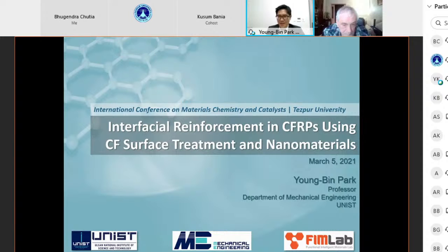I worked with a professor in chemical engineering. So she directly synthesized transparent graphene film on an epoxy-based substrate. It's a little hard to see here, but there is a transparent sensing film which has been directly grown on the epoxy substrate. And when this substrate undergoes mechanical deformation, bending in this case, the transparent graphene film can sense and measure those deformations, the flexural deformations.